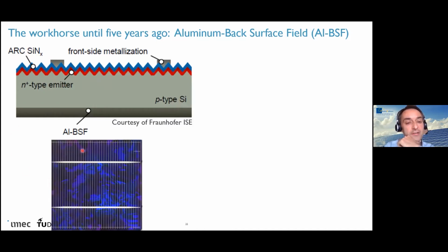So it looks like this from the front. You have very thin lines, which we call fingers, and they are connected by bus bars, which are a little bit bigger transversal metal lines. And then at the rear, the whole surface is covered by aluminium, which forms together with the silicon a silicon aluminium alloy that acts as a back surface field.